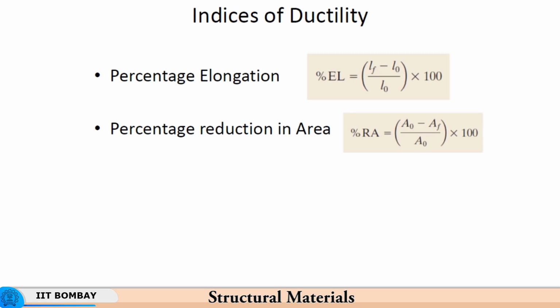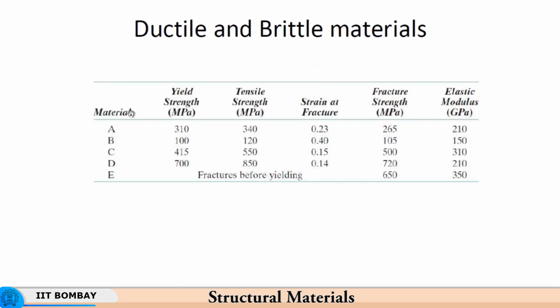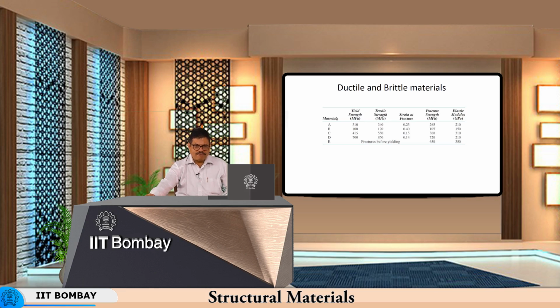With a high value of n, you will get a large reduction of area in uniform deformation. If the rate sensitivity, that is m, which refers to viscous effects, is more, then you will get, even after neck formation, even after localized deformation, a large amount of reduction in area. So, the rate of reduction in area with strain becomes more and more gradual as the value of n strain hardening exponent and rate sensitivity index increase. So, you have therefore different materials here which are given with different degrees of ductility, different Young's moduli.